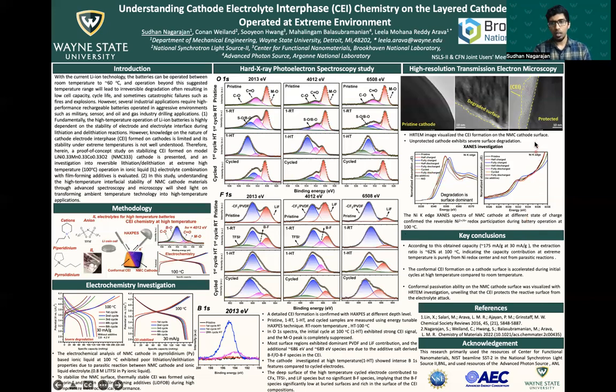Based on this work, we have obtained various conclusions. The first is that the obtained capacity is purely from the nickel redox couple. And the cathode interface formation is accelerated at high temperature, and the passivation layer is protecting the surface from electrolyte attack. So if we understand the rationale of the science, we'll be able to develop high temperature stable additives and high temperature stable ionic liquids for high temperature lithium battery applications.